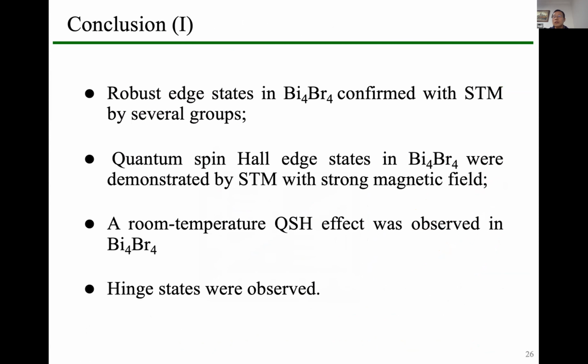So for a short conclusion of this section, I showed you that robust edge states in bismuth bromide can be observed in STM by several groups. We observe quantum spin Hall edge states in bismuth bromide, in particular with a strong magnetic field, and we observe the room temperature quantum spin Hall effect in this material. We also observe hinge states and confirm that this might be a higher order topological TI.